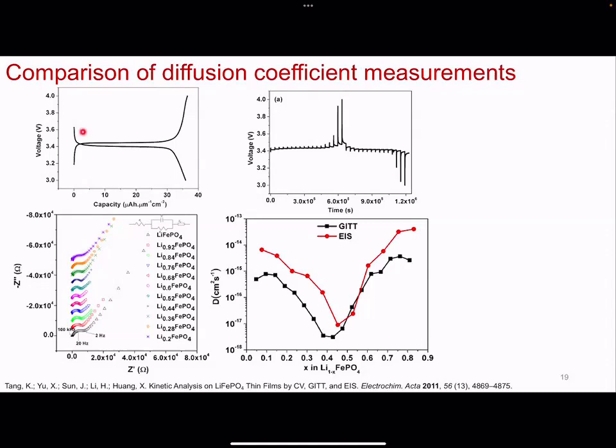So in terms of 1 phase, you're basically operating as close to 0 or as close to 1 in terms of lithium. So any values of diffusion that you see reported in the literature, that's just the apparent diffusion coefficient for the 2-phase region.